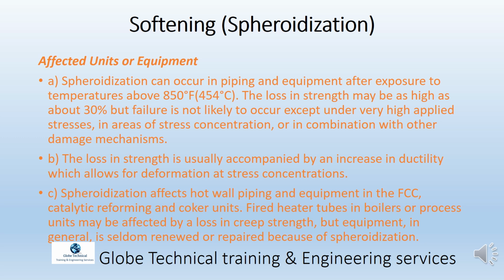B. The loss in strength is usually accompanied by an increase in ductility which allows for deformation at stress concentrations. C. Spheroidization affects hot wall piping and equipment in the FCC, catalytic reforming and coker units. Fired heater tubes in boilers or process units may be affected by a loss in creep strength, but equipment, in general, is seldom renewed or repaired because of spheroidization.